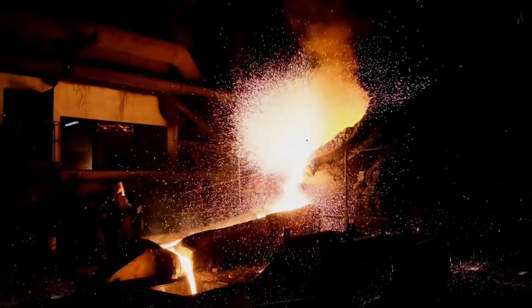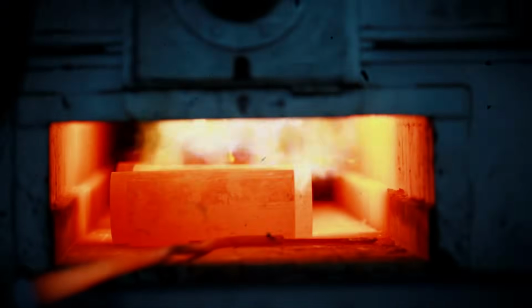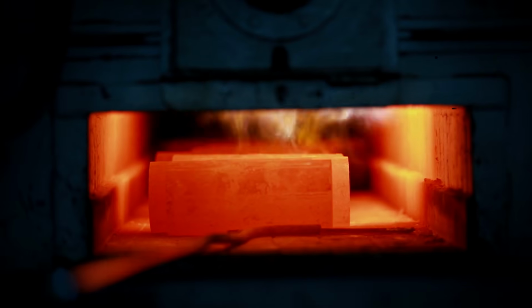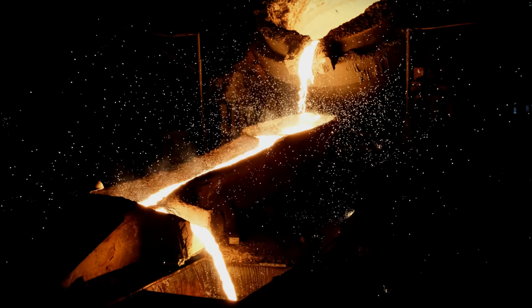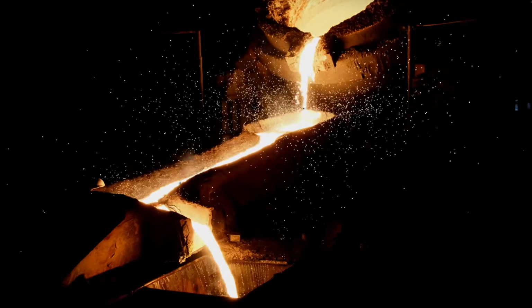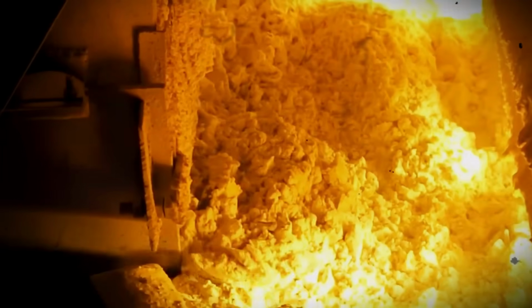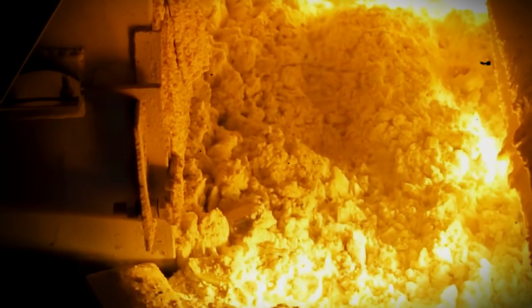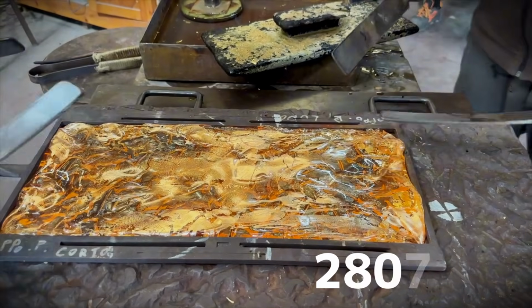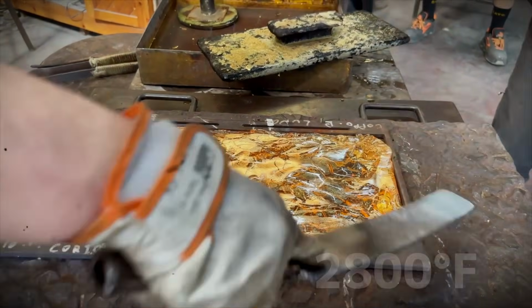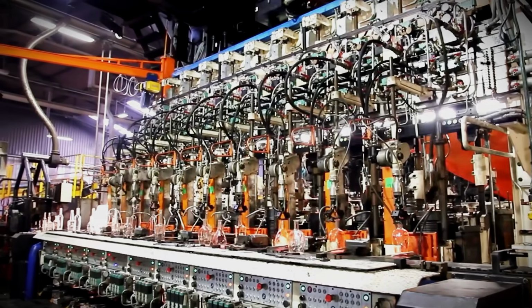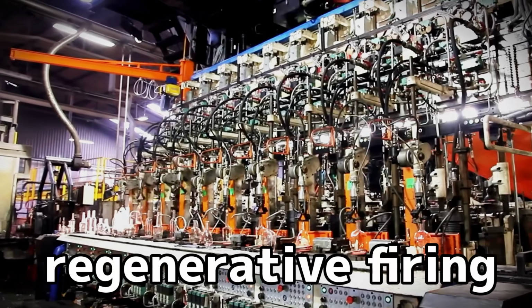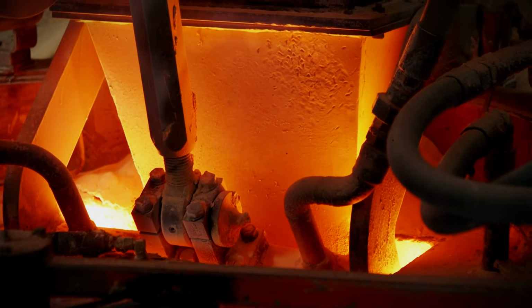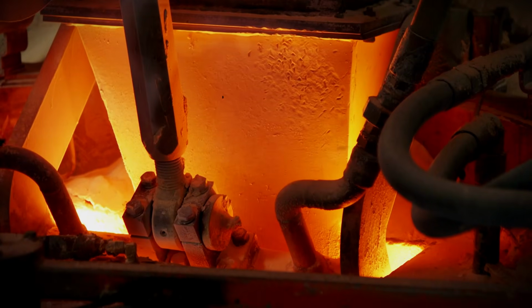And this is where it gets intense. The furnace is an absolute beast, stretching over 120 feet long, 40 feet wide, and standing 3 stories tall. Inside, natural gas burners fire continuously at 2,800 degrees Fahrenheit, hot enough to melt steel. The flames switch sides every 20 minutes in what's called regenerative firing, where exhaust heat preheats incoming air, boosting efficiency up to 50%.